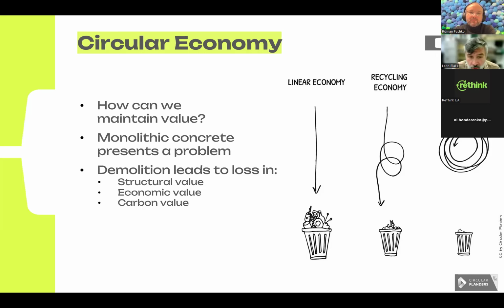A concrete beam that's turned into rubble no longer performs its structural purpose. It loses economic value as a beam is converted into rubble, because rubble is far, far cheaper than monolithic concrete. And it also loses carbon. We take concrete with a carbon footprint of typically 250 kilos per cubic meter, and we're using it to replace, typically at the moment, aggregate that has a carbon footprint of 15 kilos per cubic meter. This is an incredible loss. Okay. So what else can we do?